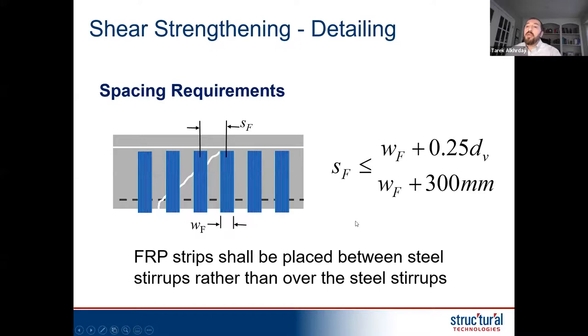And the last thing to keep in mind, maybe not the last, but one of the things, is that the spacing is also an issue that we need to consider. I cannot put the FRP strips too far apart because a shear crack can happen right in between them and they won't be effective. That's why I need to keep them close enough to make sure I capture any shear crack. And there is some criteria for that, such as do not exceed 1/4 the effective depth or 300 millimeter max. This will guarantee me that we'll always have at least 2 or 3 strips that will cross any crack.